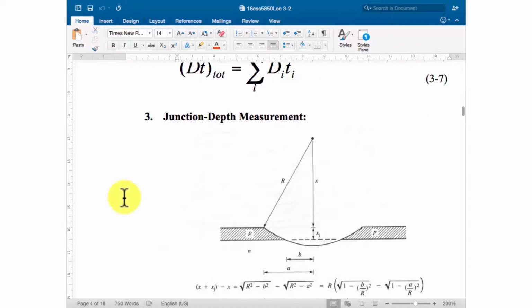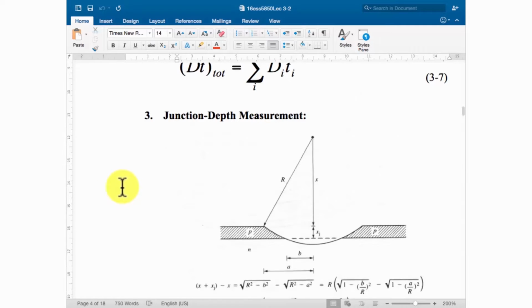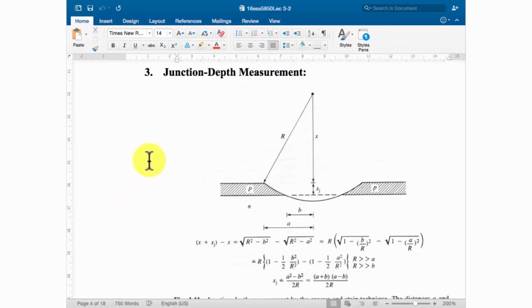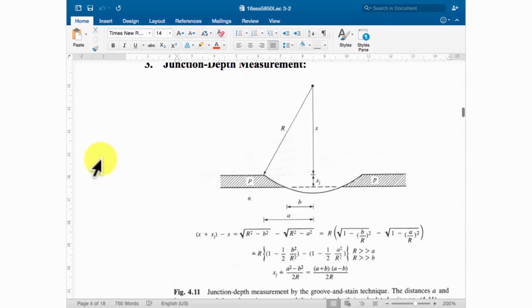After diffusion, sometimes we need to find out the depth of the diffusion: how deep you diffused the impurity into the substrate. So we need to use a very special method to do the estimation. Because the thickness is usually very thin, only a couple hundred nanometers or even shallower, it's not easy to do a direct measurement. So usually we use a wheel to cut the surface into a circular shape. In this circular shape, we change the thickness into a length here.